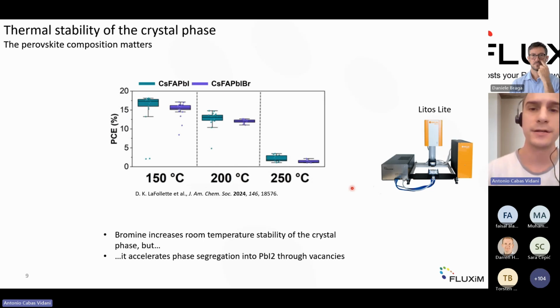And here they compared, here it's a bit different because they didn't study directly the stability, but they did parallel JV testing in order to see the impact on PCE. And as I mentioned, this is a key part of understanding stability. And what they compared was absorber with and without bromine. In this case, the use of bromine is that it increases the room temperature stability of the crystal phase, but at the same time, it accelerates the phase segregation.